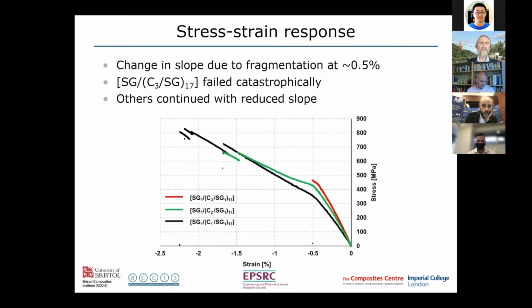So this is the response. So you can see that we do get a nonlinear response with a change in slope at about 0.5% strain, which is the compressive failure strain of these carbon fibers. With the triple ply, you see that as soon as that fragmentation starts, the whole specimen fails. But when we have two or one ply together, then we get a change in slope. It still increases, but then at a certain point, it fails due to the delamination, but at a much higher strain.